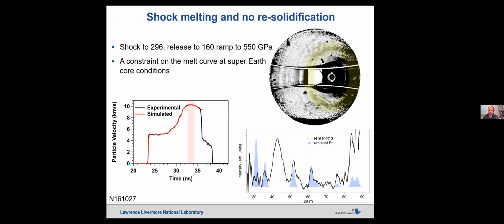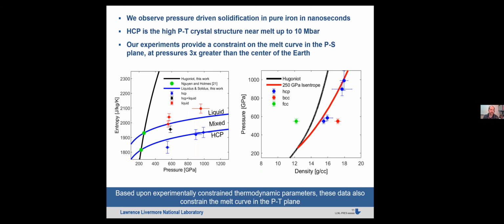And then as you increase the entropy even further, shock it to a higher pressure, shocking to 300 GPa, then releasing to 160, then ramping back up to 550 GPa, we observe no solidification. So we observe only this diffuse liquid scattering feature, sort of underlying this yellow highlight here, also shown in the line out here. We don't see any signatures for HCP or any other solid phase. So this again provides that constraint in the pressure entropy plane on the melting curve.